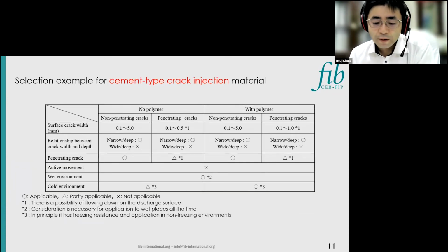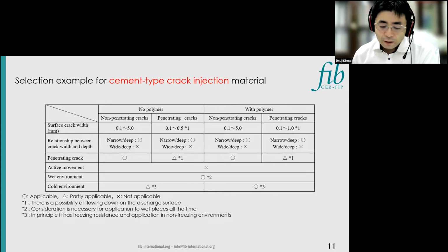Next, about cement type materials. Cement type include products with and without emulsion polymers, but products containing polymers, which have higher adhesion, are common. For application in cold climates, products containing polymers are more resistant to frost damage. It can be applied even in wet conditions, but since materials will not cure in cracks with a large amount of water supply, it is necessary to apply materials that can be cured quickly. And cement type materials generally have no flexibility, so they are not suitable for cracks with opening and closing behavior.